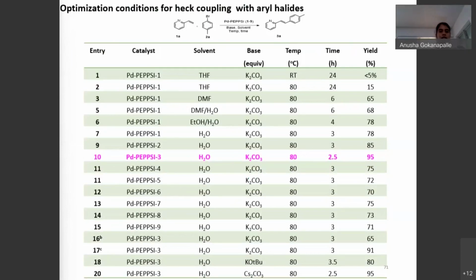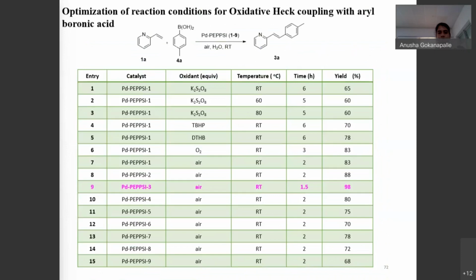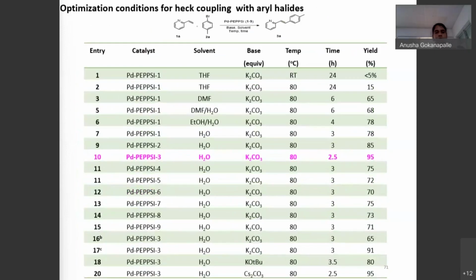When we increased the temperature to 80 degrees centigrade, we got 15% of yield. Among all these Palladium PEPPSI complexes, Palladium PEPPSI 3 gave the best results in water. It gave 95% yield in 2.5 hours because it has a bulky triisopropyl group.